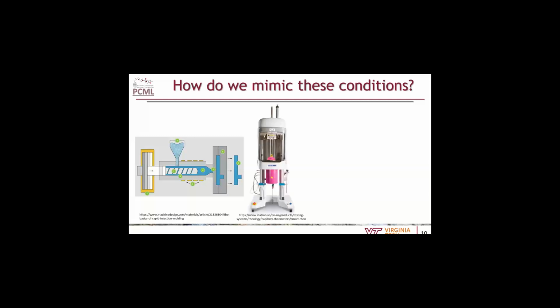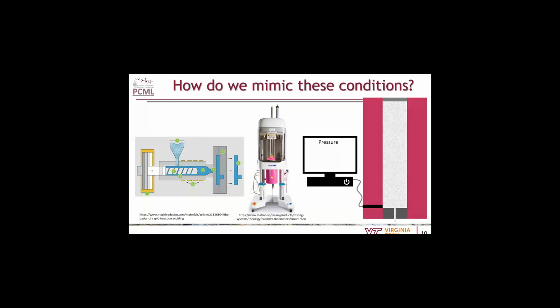One of the easiest ways to mimic this is to look at a capillary rheometer. Traditionally, we have used an Instron SR20. That's what we had in the lab when I arrived there, and we've since gotten some other functionality. But this is really nice for polymer melts because it's got roughly a 60 milliliter barrel that you can fill with polymer, melt it up to 300 some odd degrees Celsius, and then push your material out.